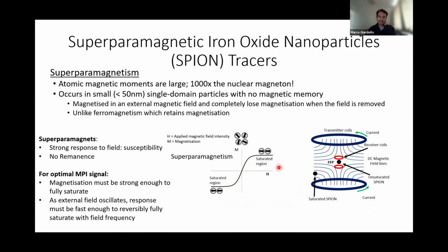because that signal intensity is related to the height of your magnetization, and it rapidly saturates and desaturates as fast as possible. You don't want the ones here, and you only want it to respond to the sinusoidal field in that point as well. You don't want it to be sort of here kind of responding, if that makes sense. So that's what you want. You want a high magnet, as much magnetization as you can, and a rapid fluctuation of its magnetization as the drive field sort of passes over.